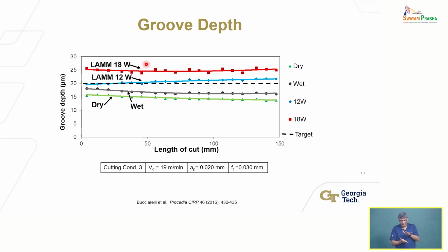Which means that it's going to expand further and the depth of cut will increase, even if the tool is at the same position. That's what's happening. But that's an easy problem for me to solve. I can compute how much energy I'm inputting. I can estimate the expansion, knowing the coefficient of thermal expansion, and I can compensate for it, which means that if I want to produce 20, I start with something less as my programmed depth of cut. There's a simple solution to it, right? So that's one solution. But what you do see is that initially, by optimizing the laser power, you can achieve the depth required. That's the point I'm making.